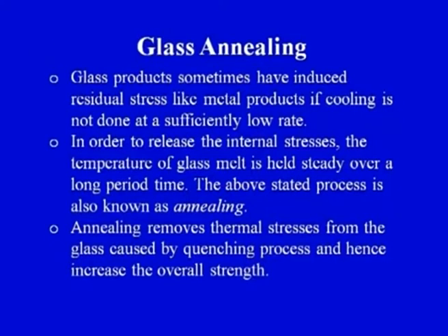Glass products sometimes have induced residual stresses like metal products if cooling is not done at a sufficiently low rate. So, the amount or the type of stresses that are developed will depend specifically on the cooling rate, and we have to manipulate the cooling rate in such a way so that we do not get any stresses in the final product. But in many cases, because of the processing steps involved, because of the specific requirements of the product, induced stresses are found in the final glass products.